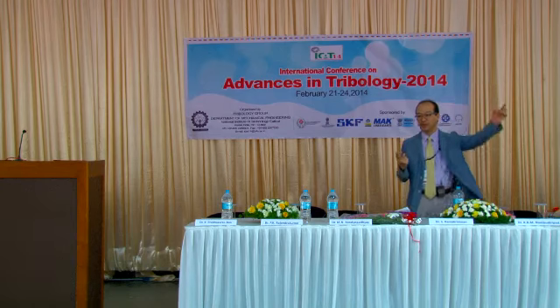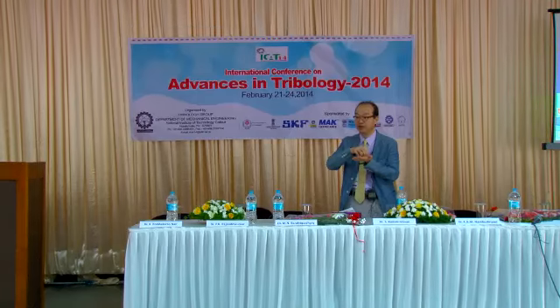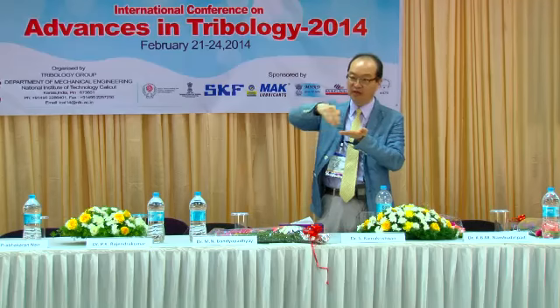So if you look at my experiment where we use a bushing for up to 150 kilometers or 200 kilometers, the height of removal is about 0.00001 nanometer per cycle. In other words, when it's sliding, rotating against the counter surface, it means that there are cycles at which there is no wear, probabilistically. So if I use that analogy, I can also claim that for 1 kilometer, I only get a fraction of an atom of wear. You see what I mean? So it really depends on the viewpoint that you have and how you approach that kind of problem. In terms of height, we can claim that.